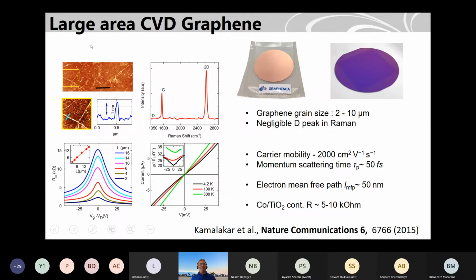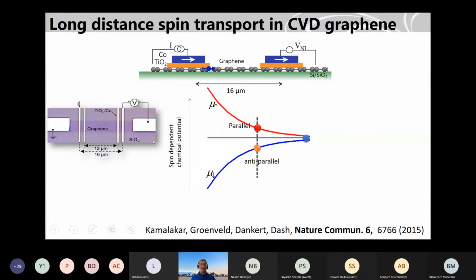And this is actually a large-area CVD grown graphene, because if you want to make an interconnect more than 100 micrometers, you need to look for large-area graphene. We published in 2015 that we can show very long distance spin transport. This graphene is commercially available. You can buy it from the market, and you can transfer it on a 4-inch wafer. It's a big wafer, and then you can take a small piece to do your experiment. But it's wafer-scale graphene.